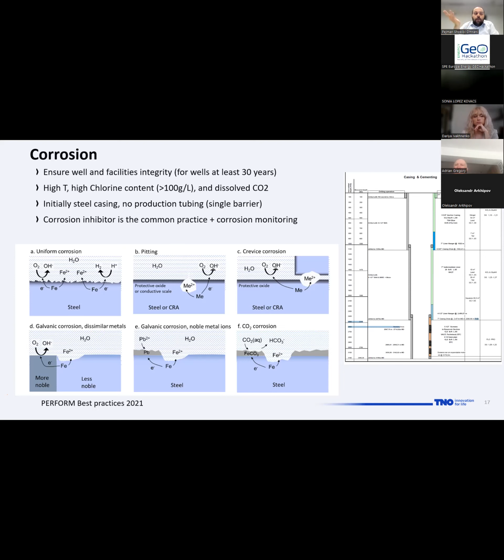Currently, the most important way to mitigate and control this is, of course, to monitor the corrosion. And inhibitor injection is also one of the very regular practices for controlling the corrosion. We see now there are more developments in the market to go also for GRE liners. So in this case, you do not have metal contact with the brine in the production well, and then you can minimize your corrosion risk quite a lot.